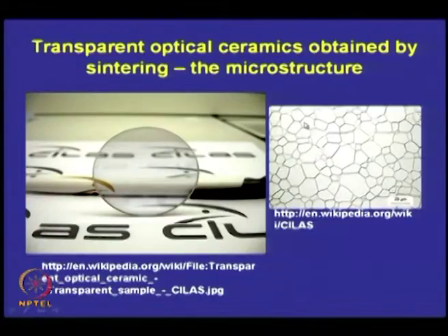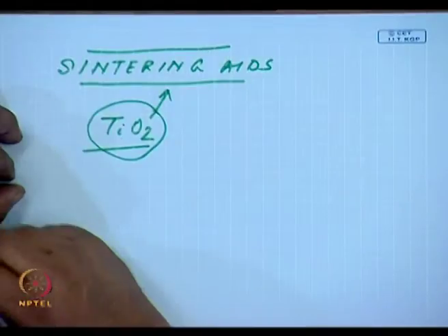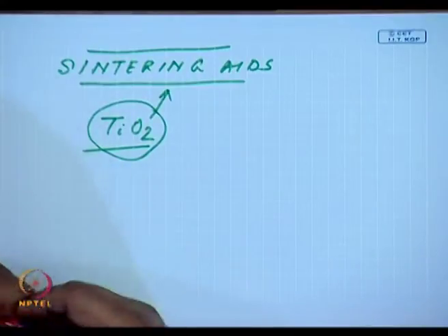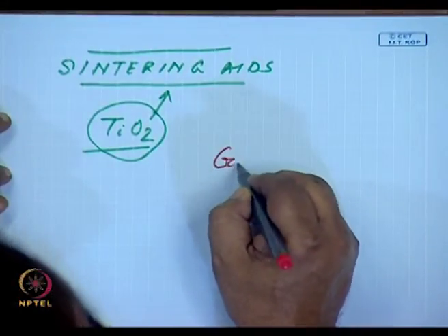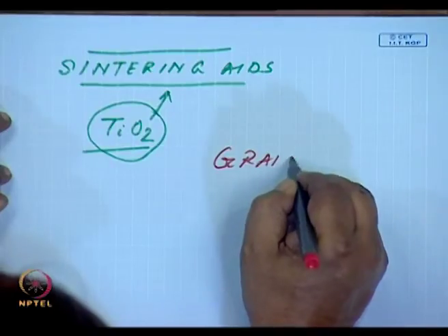Let me look at the slide again. This particular structure - it's very easy to say the grain sizes are uniform, leading to a transparent ceramic. Here they have used titanium dioxide as a sintering aid, true, but they have also used another material which is a grain growth inhibitor.